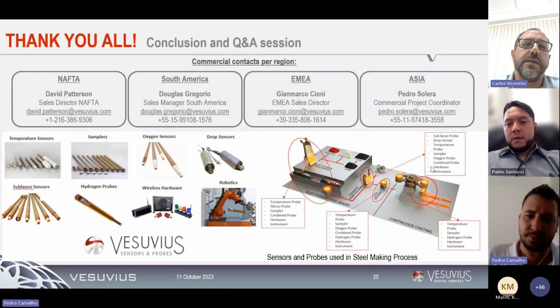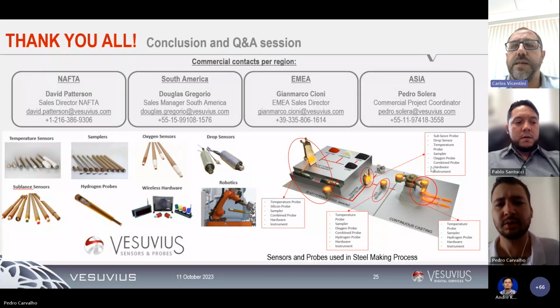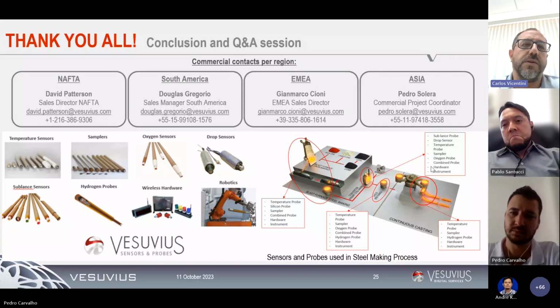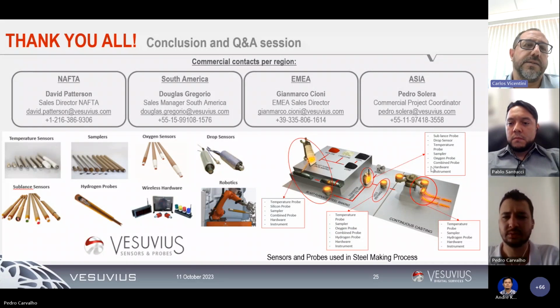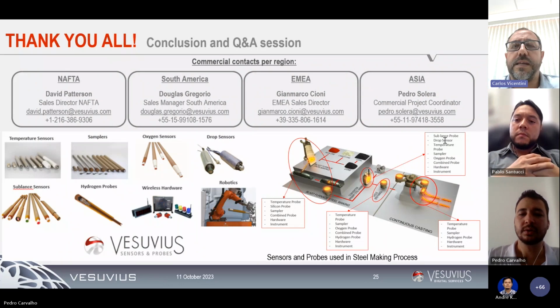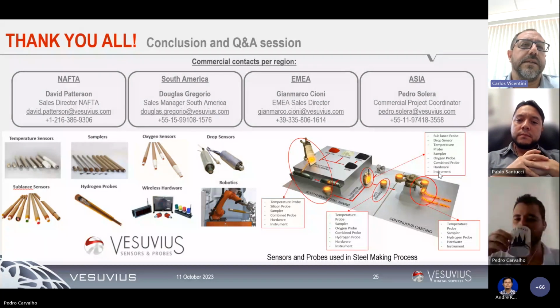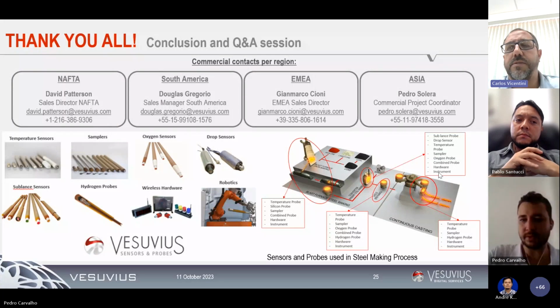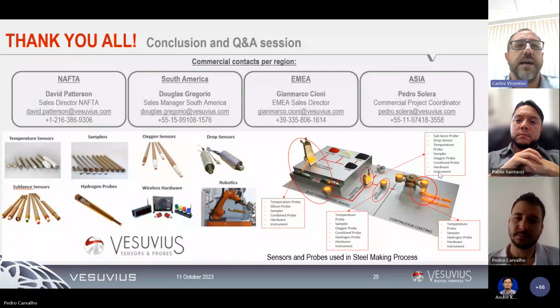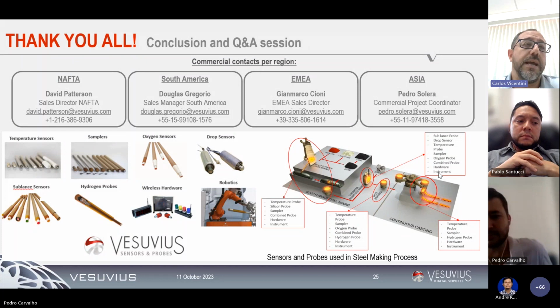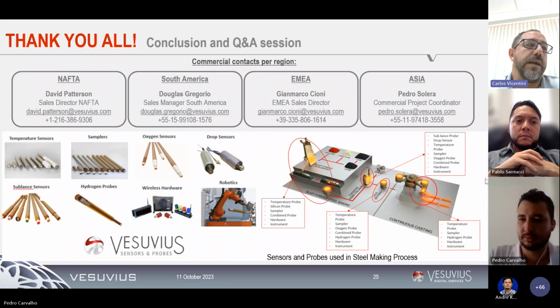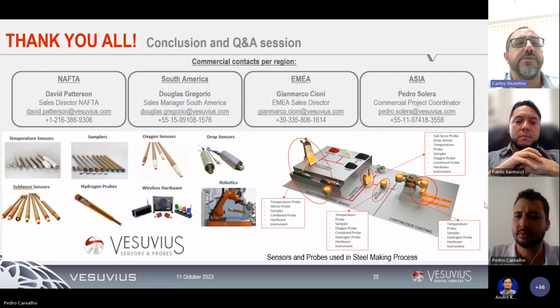I think about the calibration. Yeah. We really recommend using the bottle. In fact, bottle or line gas is not a big problem. The question is the purity. To take good measurements of hydrogen, it's very important to use high purity nitrogen as the base of the measurement. And usually, if the steel mill has good tubes and a good line that guarantee the purity when it enters our system, no problem.